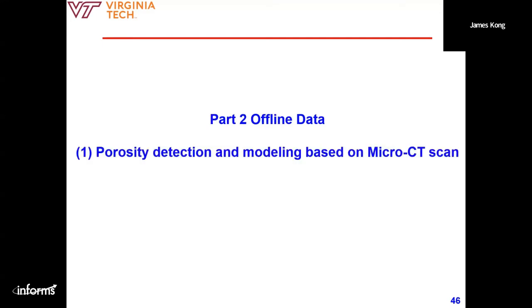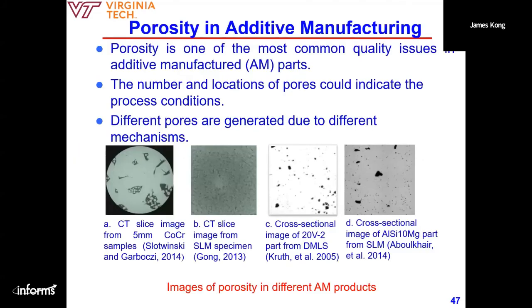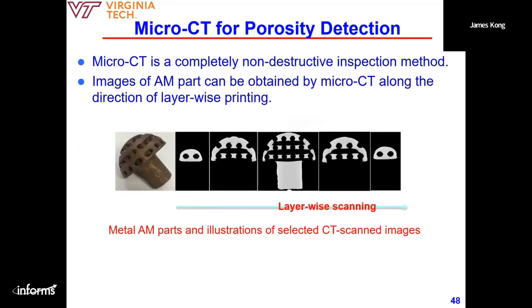So the first one is micro CT. We use micro CT, scan the parts and see the patterns of the porosity. Porosity for metal printing is what we really do not want to see, okay? And in bio printing, perhaps that's what we want, to make the biomaterial more similar to the actual material with some porosities. But again, for the metals, we do not want to see it.